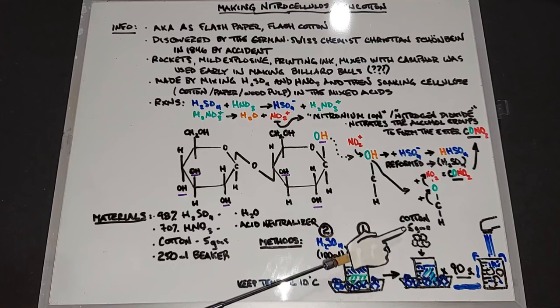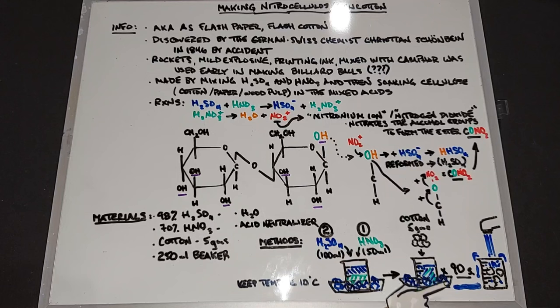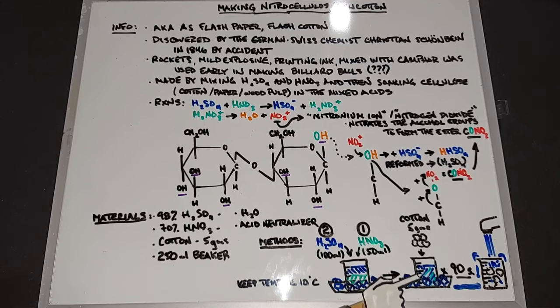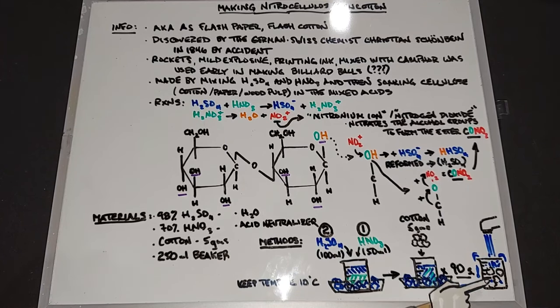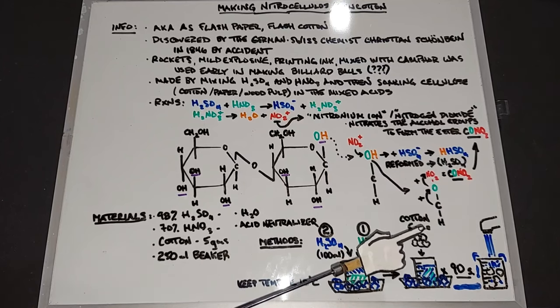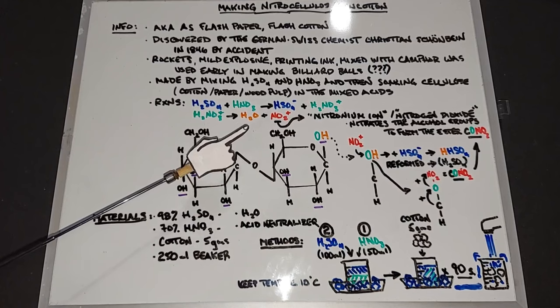Once you've gently stirred your acids and got them mixed well, add your five grams of cotton and push it under to make sure it's soaked all the way through. Because of the solutions I'm using, the percentages and the ratio of sulfuric and nitric acids, I've done multiple experiments and it only takes 90 seconds to nitrate the cotton properly. If I leave it in longer, the cotton gets mushy and eventually completely useless. After 90 seconds, I decant the acids off, then start pouring water into the cotton until it's thoroughly washed. Once it's dry we'll light it and it should burn very quickly. Let's go do this.